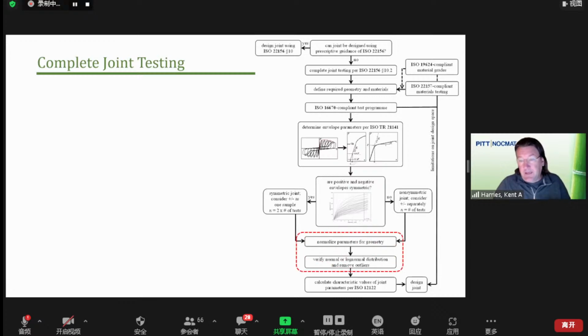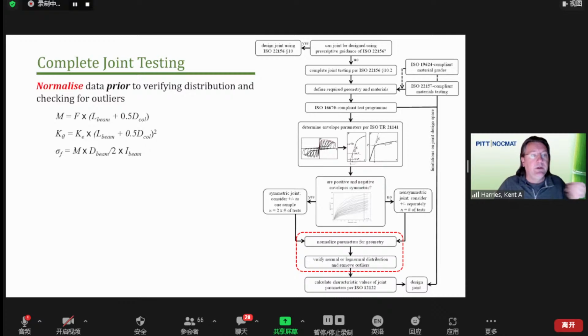So now we've got to normalize our parameters. It is not appropriate, typically, when we're looking at bamboo, unless we have very, very tight control, to simply look at force and displacement. We want to look at moment, rotational stiffness, and stress, because, of course, these are affected by the dimensions both of the test setup, the length of the beam, and the dimensions of each of the elements. And these vary. It's bamboo. So we're going to normalize our data in terms of moment, rotational stiffness, and then ultimately extreme fiber stress.